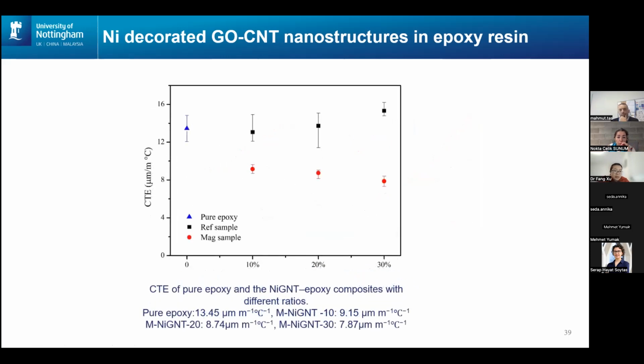We also measured the CTE, since coefficient of thermal expansion is an important property for thermal management materials. We want lower CTE, to better match other materials, since polymers always have high CTE. We can see the magnetic controlled sample has lower CTE compared to other samples.